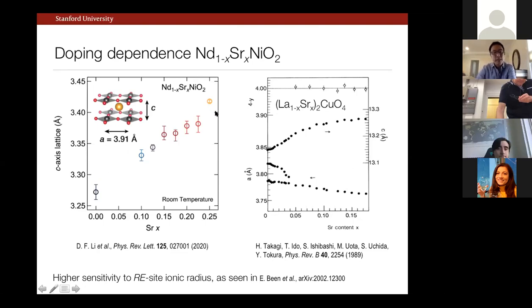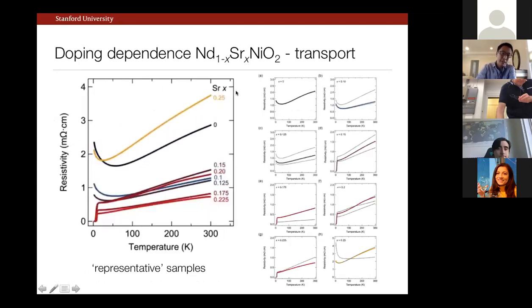And of course, there might be competing electronic degrees of freedom, but in any case, this is within our expectations. And in terms of the resistivity as a function of temperature, I'm going to show you first what I'll call representative samples. So here's the undoped neodymium nickelate. It has this low temperature upturn. Okay. And as we start to dope strontium into the neodymium site, you can see that it comes down. We have a range of superconducting samples. And then if we want to use this language for overdoping, we return back to this insulating upturn.